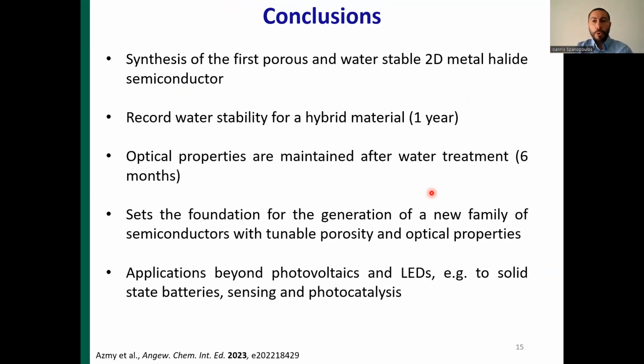Summarizing, we report here the synthesis of the first porous and water-stable 2D metal halide semiconductor. The material exhibits a record water stability for a hybrid material of more than a year. Importantly, the optical properties are maintained after water treatment, at least for 6 months in water. Of course, this sets the foundation for the generation of a new family of semiconductors with tunable porosity and optical properties. As you can imagine, by means of molecular engineering, the porosity can be finely tuned. And this allows this unique new family of materials to be utilized in applications beyond photovoltaics and LEDs, such as solid-state batteries, sensing, and photocatalysis.